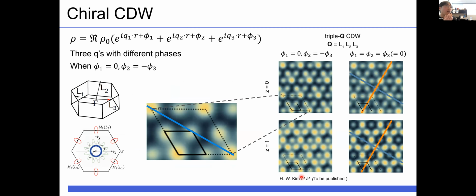So to break the chiral symmetry of the CDW, the phases should be different. These are the images made with 3 different phases. If you see the figure at the center, the blue line, which was the mirror plane of the achiral CDW, is not a mirror plane anymore. Below the blue line is brighter than above. And also you cannot find other mirror planes or inversion centers in this case. So with different phases of the CDW, we can make chirality.